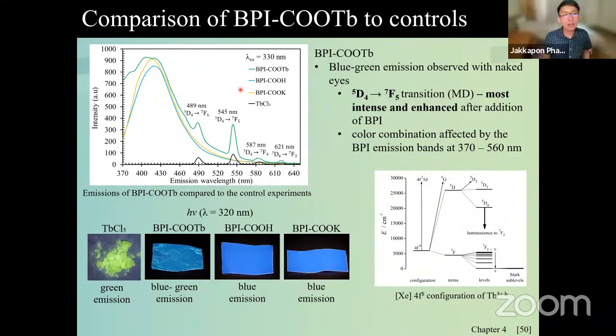The same thing happened in the terbium. When I add in the ligand, you see that the brightness of the photoluminescence is much higher, which is much better than just using the ligand or the lanthanide itself. It might be because of what is called a quenching effect. I'm going to test it for VOCs now.